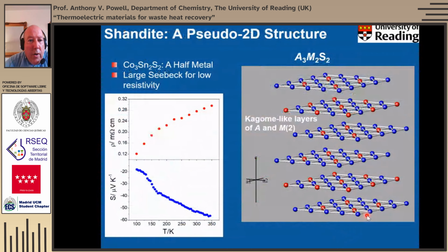So our first foray really into sulfide thermoelectrics was what are called shandite, based on the shandite mineral. It's a half metal. It's unusual that it has a very large Seebeck for such a low resistivity. So at 350 Kelvin, its Seebeck approaches minus 60 microvolts per Kelvin, and yet the resistivity is still less than 0.3 milliohm centimeters. So it's quite an unusual combination.